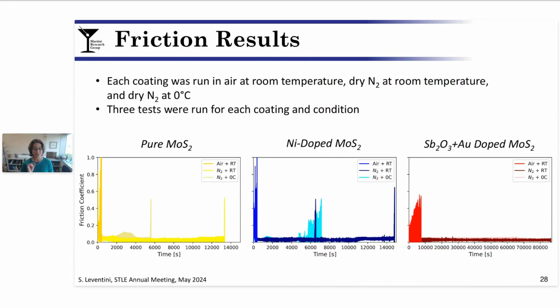And also, if you're perceptive and you're looking at the x-axis, you can see that the rightmost plot, the x-axis is much, much longer, already giving us hints that the antimony oxide gold doped coating is lasting much, much longer than the other two.